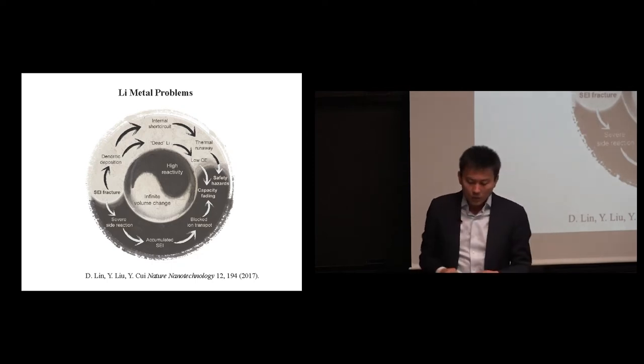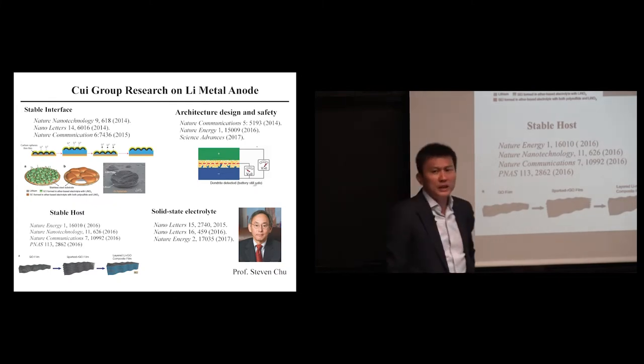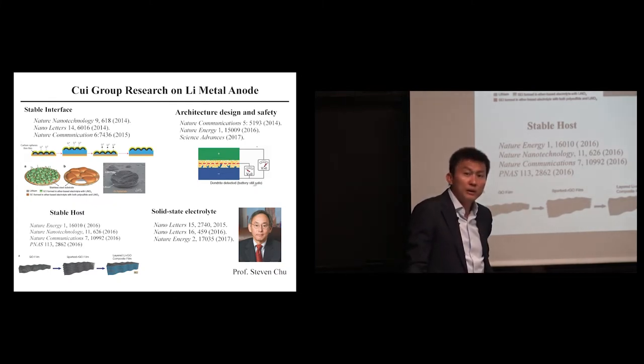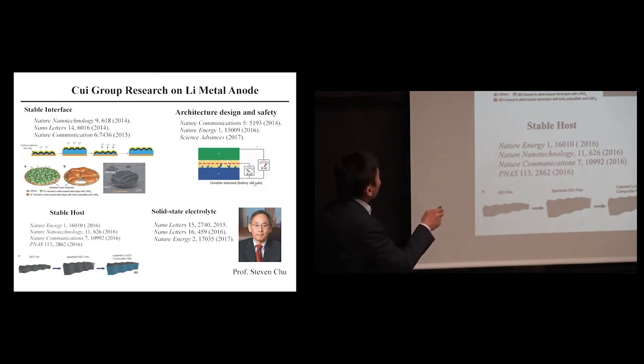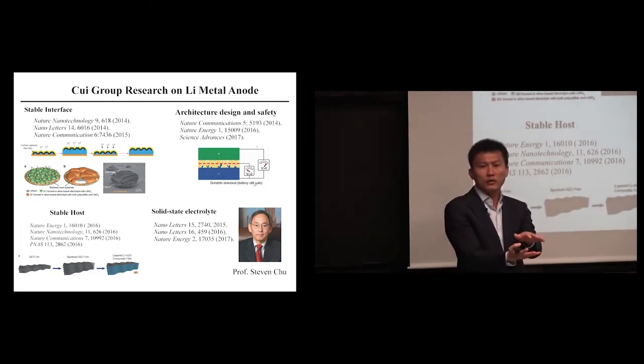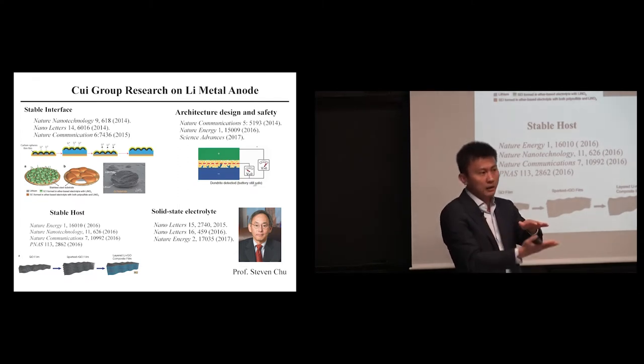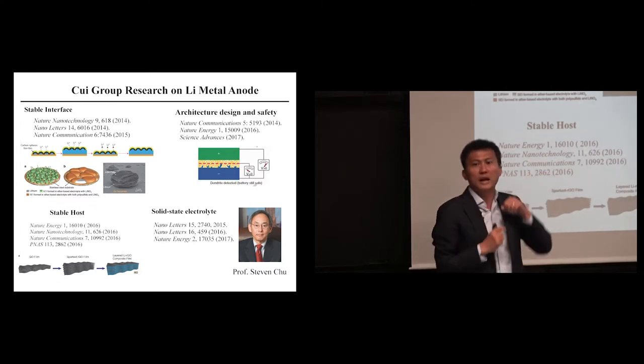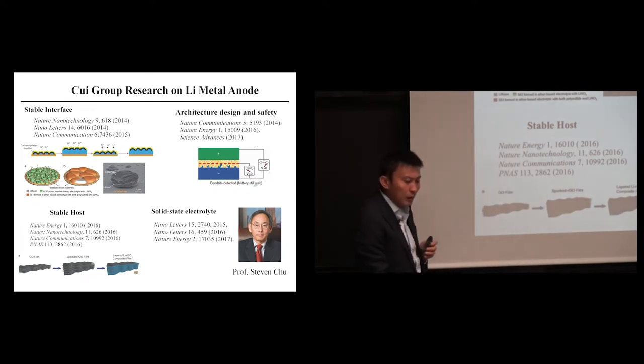So looking at this, as a Chinese, probably as a Korean as well, you like to draw something like this. You say, well, down to the bottom, what's the cause? What's the root causes right there? There's two right here. High chemical reactivity of lithium. And also this relative volume change is infinite. Going to filled state, empty states completely. This change is too dramatic. The rest are the phenomenons. You see the bad things taking place. So in order to solve all this problem, let's come up with a solution for the root causes first. So we built a research program. Steve came back to Stanford in 2013. And we have a really nice chat. We say, what's the most important material we work on? We all identify metallic lithium. We got to solve this problem. We need to build stable interface, overcome the high chemical reactivity issue.